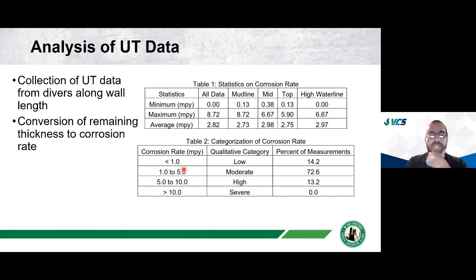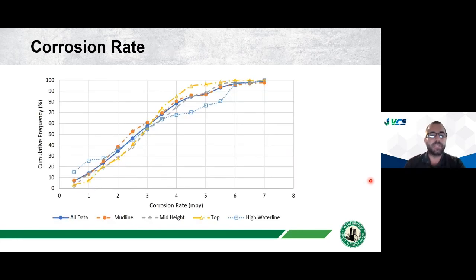We can take that data and see that a corrosion rate of 1 to 5 mils per year is a moderate corrosion rate, and about 70% of the samples were in that moderate range. We had about 13% in a high environment and 14% in the low. So most of them were in the moderate. Then we can look at it statistically, at corrosion rate and the cumulative frequency for the different environments. Around 50%, we're in the high 2s for the corrosion rate, but we see corrosion rates all the way up to 5, 6 mils per year. And so we can design cathodic protection mitigation systems based around these mils per year.